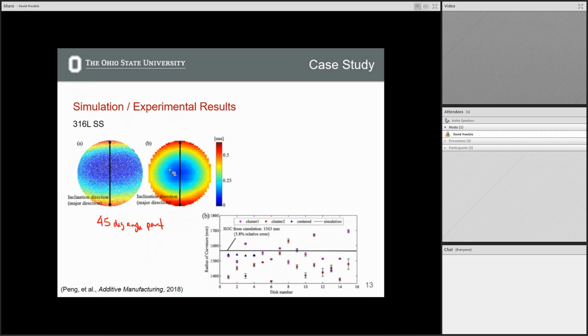This is looking at deformation of the angled parts. This is the 45-degree angle part. And this is showing the patterns if you scan it with the CMM versus what we predicted, which had some similar features. So not a perfect 100% match, but qualitatively a fairly reasonable approximation of the type of behavior we would expect here. Any questions about this thus far?